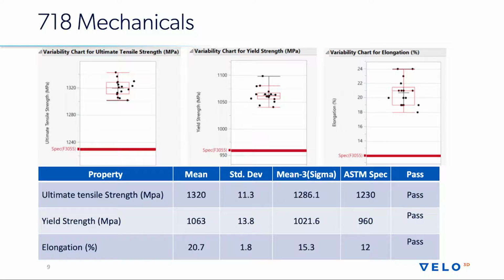So if I have a material sheet and it calls out a mean value for the ultimate yield or the ultimate tensile strength for 718, that's great, but that doesn't help me. Because if my mean minus 3 sigma is half that, then my design allowables are shot. So I wanted to present some true statistical data from our standard parameter set around at least static mechanical properties. And the thing that we're excited about here is not that we're printing material that meets ASTM F3055 spec, it's that we have a pretty good reduction in the variation of the mechanical properties.